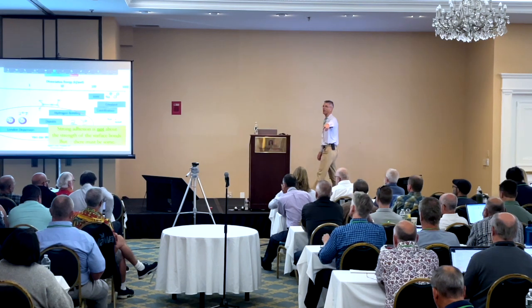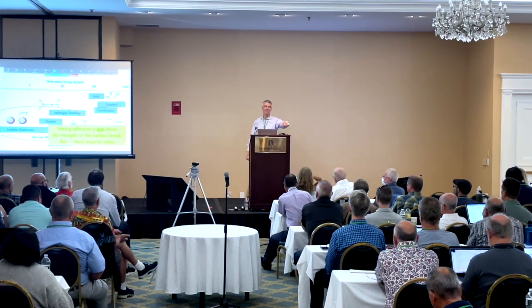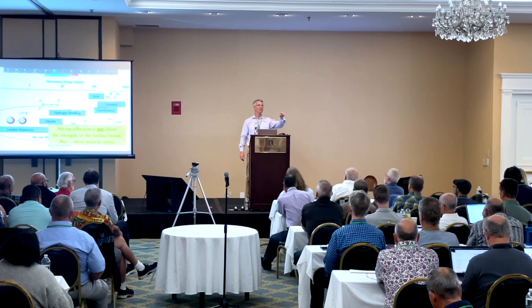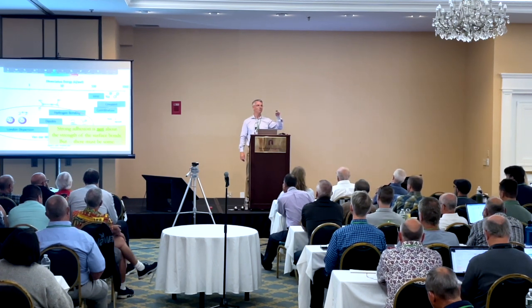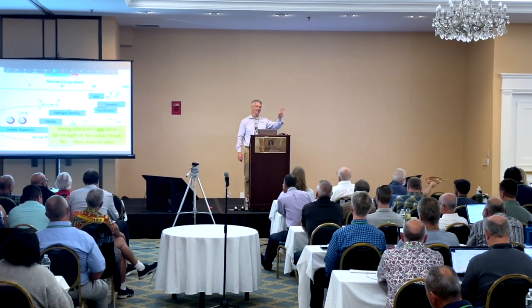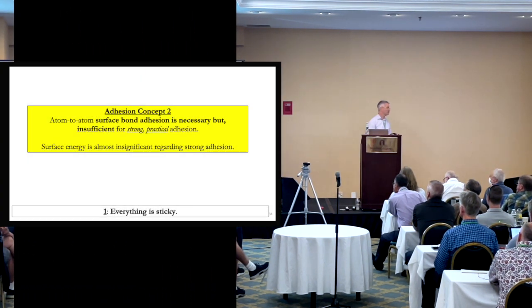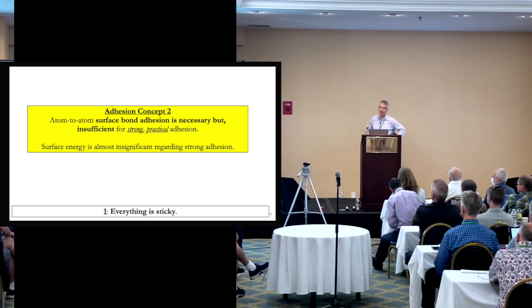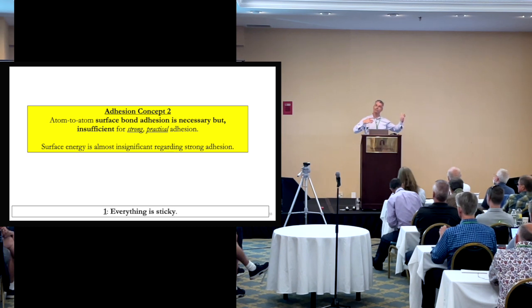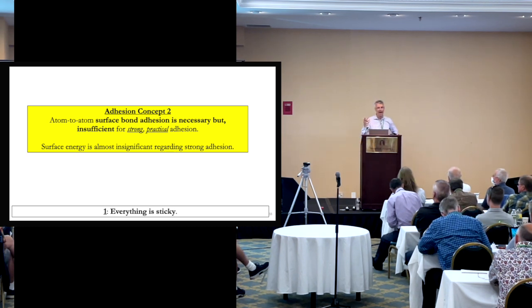So even Teflon, which we all kind of agree is the crappiest surface energy material around, we can bond and adhere things to it very easily and well. It takes the right materials and a bunch of stuff, but it's not as difficult as people think. All right, so that's adhesion concept 2. Atom-to-atom surface bond adhesion is necessary but insufficient for strong practical adhesion. Meaning, with those two gauge blocks, it's crazy strong in one direction, crazy useless in the other. But it's still these very weak bonds that all make it happen in the end. So surface energy is almost insignificant regarding strong adhesion, okay?